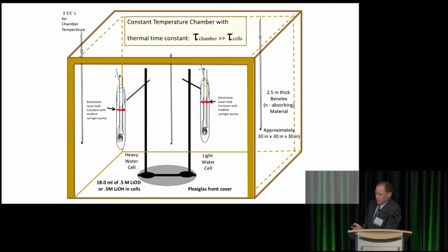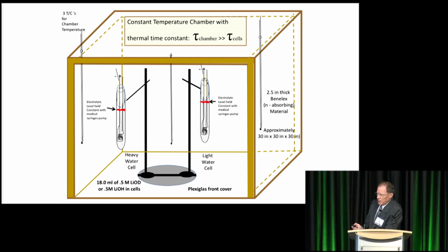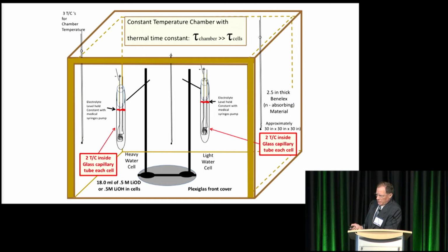The actual calorimeter is shown here, which was a large 30 by 30 by 30 casing of Benelex, 2.5-inch thick, neutron-absorbing material. The two thermocouples inside the cell were averaged for the temperature of the cell, and 3 thermocouples outside were averaged for the temperature of the media. Now, the interesting thing that I discovered is that most people use water for that media, but I found that air is actually better.